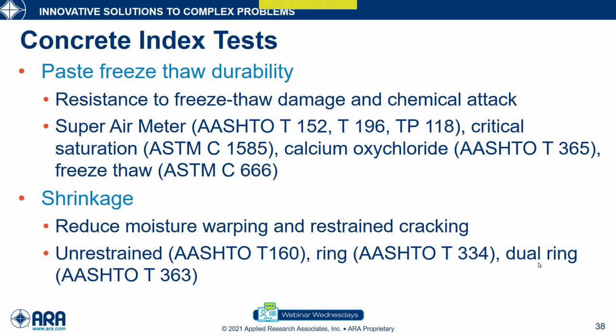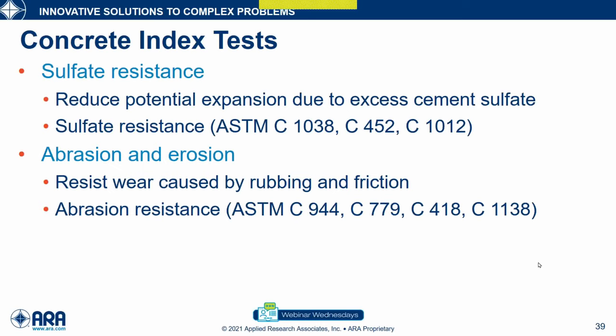And then there are tests for the freeze thaw durability of concrete, the resistance to freeze thaw damage and chemical attack, and then shrinkage, resistance to moisture warping and restraint cracking. Again, a little different from the asphalt side. There are many different tests in terms of the concrete mixture itself and how it performs in field conditions. And then finally, sulfate resistance tests to reduce potential expansion due to sulfate, and even surface abrasion and erosion to make sure you have the right surface characteristics for your concrete mixture. So there are a lot of different tests that you could do in terms of performance of the entire pavement structure, not just the mixture itself.